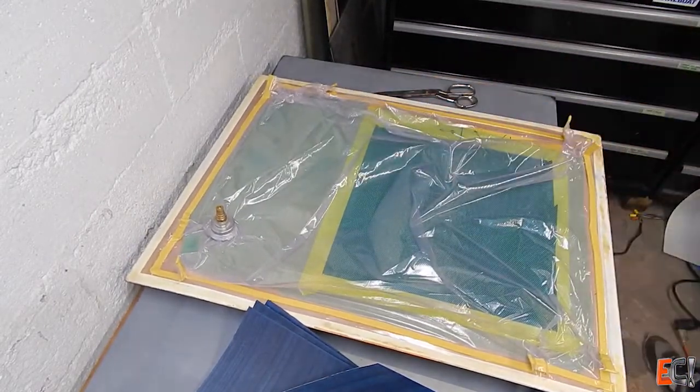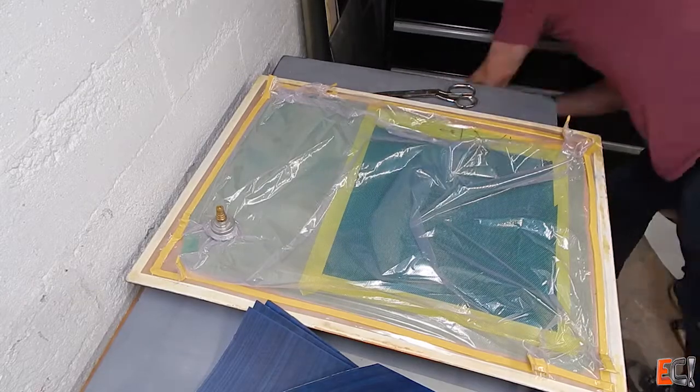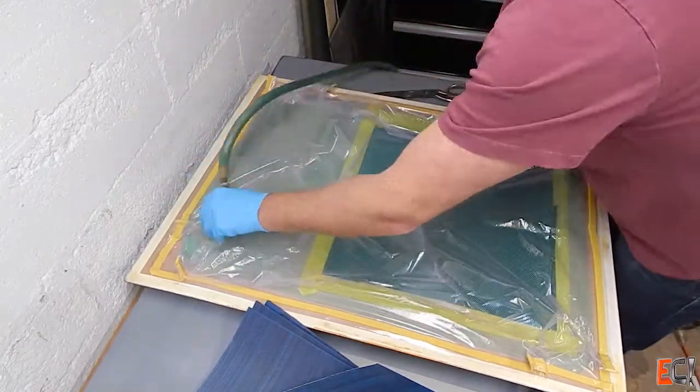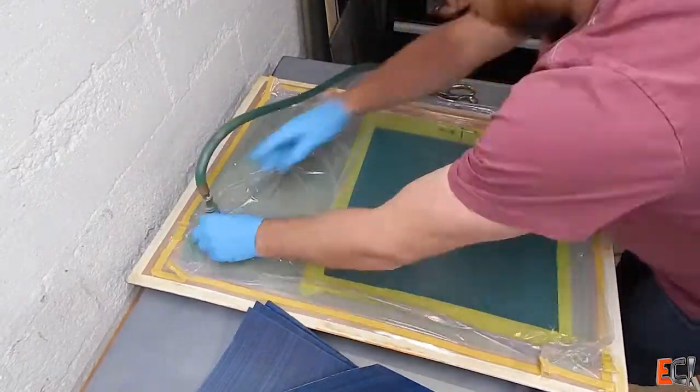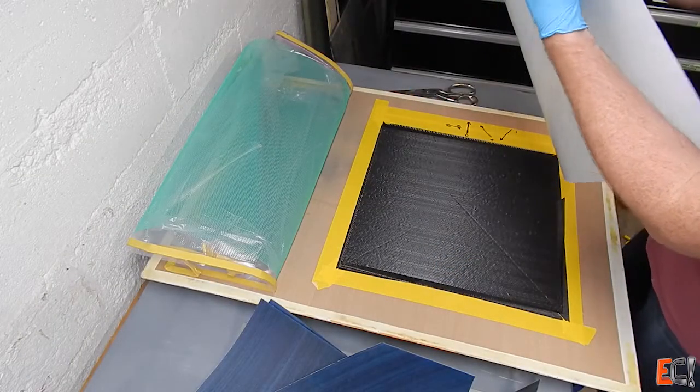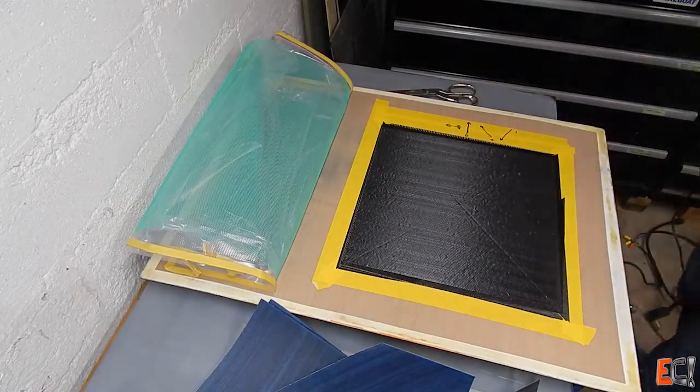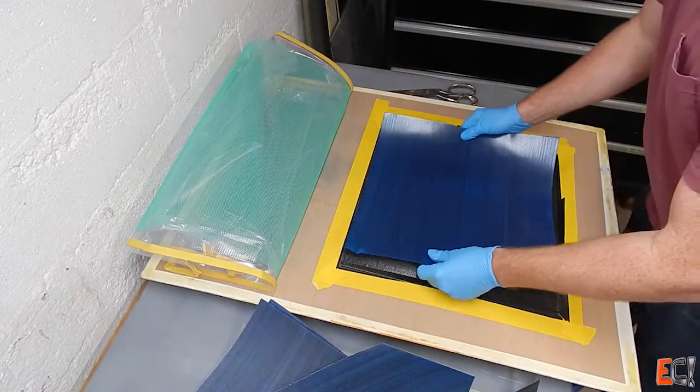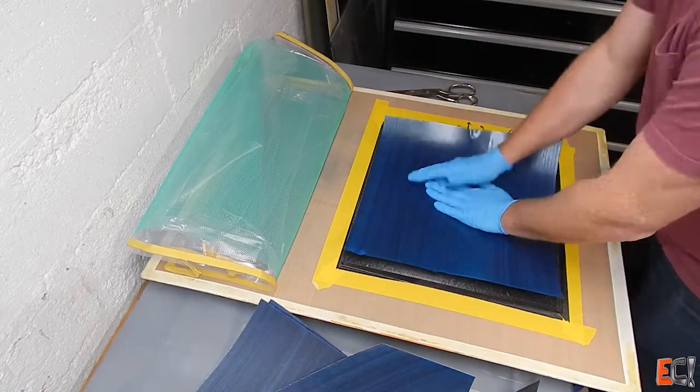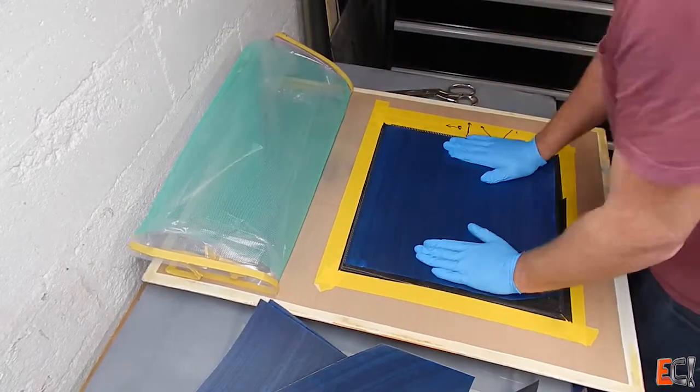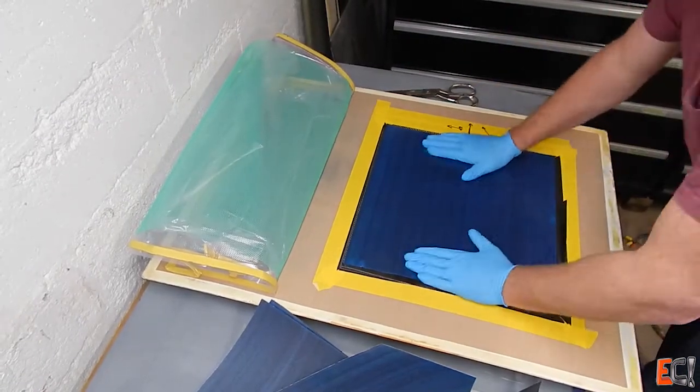And having reached about 900 grams I'm going to give it a debulk. My general rule of thumb unless I'm doing something fussy is about a thousand grams. Debulk. And so pull that off and this next ply is a 0.